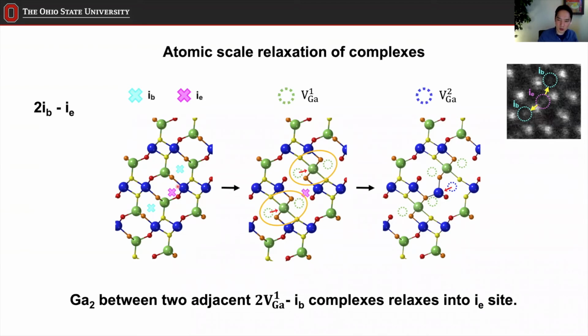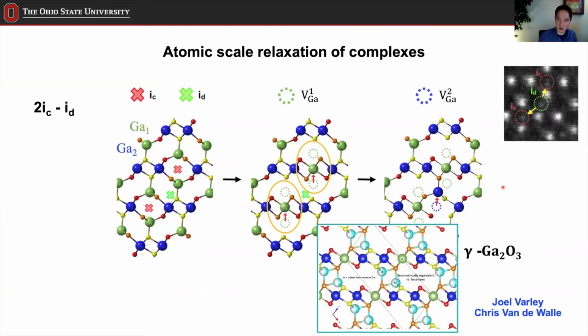Although the DFT wasn't able to model the whole thing and calculate the energy, our collaborator Joel Varley at Lawrence Livermore lab pointed out that this relaxed structure in fact has a high similarity to the other gallium oxide phase, which is the gamma gallium oxide phase. If you look at the gamma structure, you can recognize one row of atoms and then the other row of atoms, which is very similar to what we have here. These two rows are bridged by a few atoms in between, and that's similar to what happens here, although they are not exactly the same.